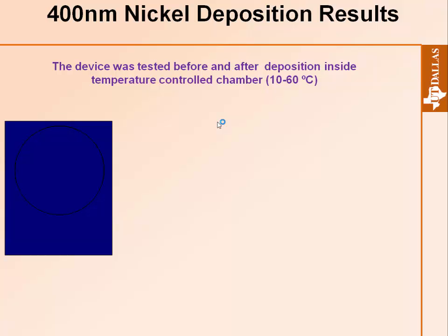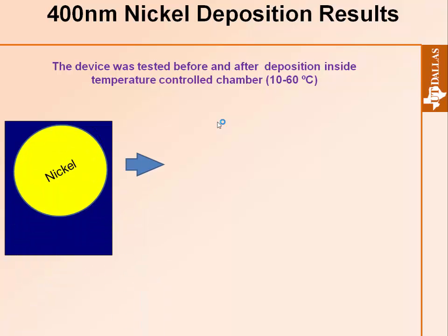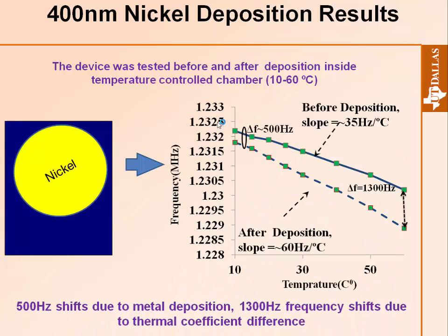To characterize and test the device, the best approach is metal layer deposition, because the difference in properties between the metal layer and the silicon membrane induces stress on the back side. This test was performed inside a temperature-controlled chamber. After recording baseline data, we deposited 400 nanometers of material.